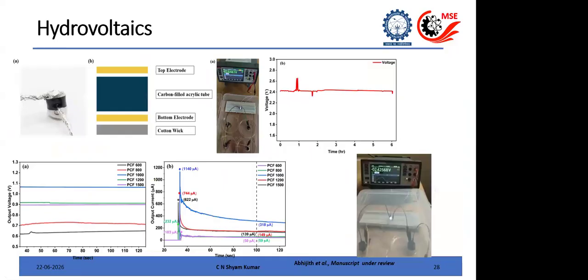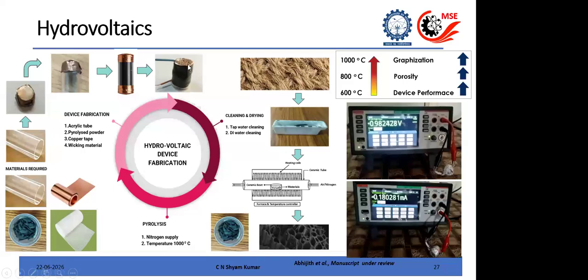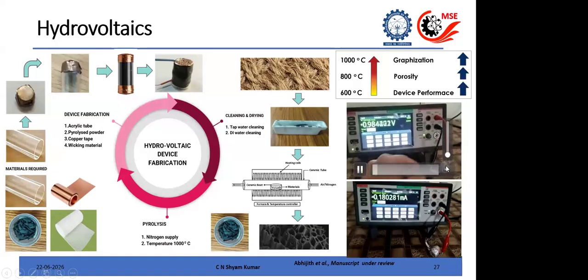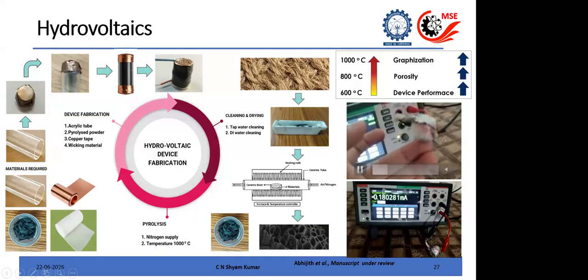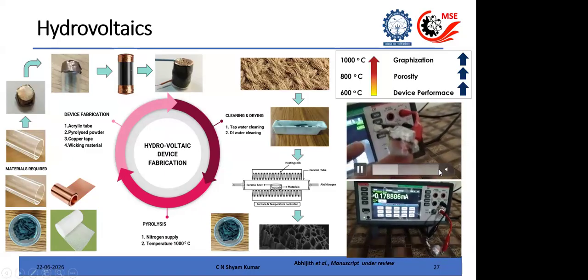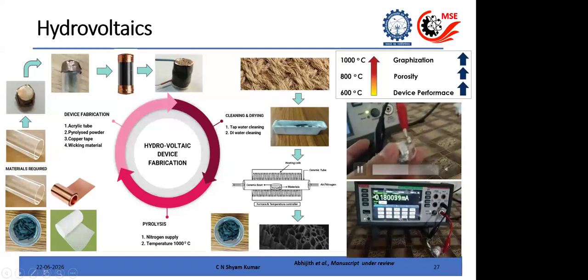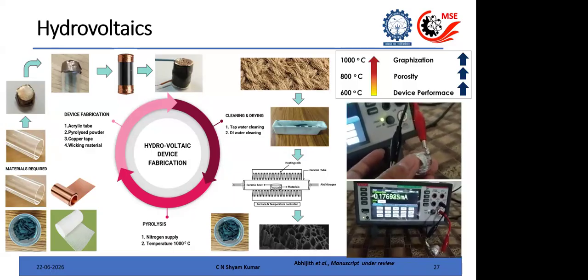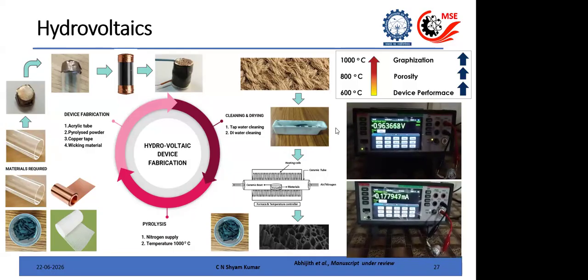So you take a tube, you fill it with carbon powder. You put a cotton wick below, because the whole thing works like this: the water will evaporate through the carbon powder in the tube. So the tube is filled with carbon, and you put it in water, so that the water will evaporate through the carbon, and there will be a flow across it, and that flow will produce some voltage and current. So this is one video, in which a small sample is giving almost 1 volt and some 0.2 milliamps of current, or 200 microamps of current. With just that small sample, without anything, it is just evaporating.